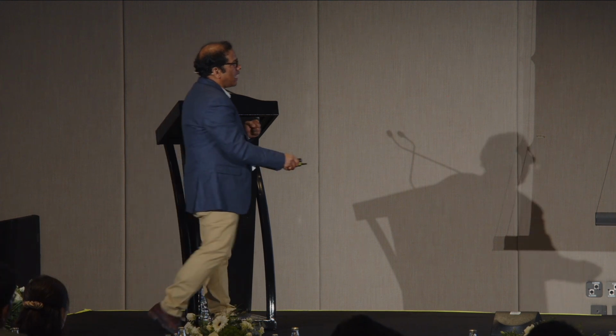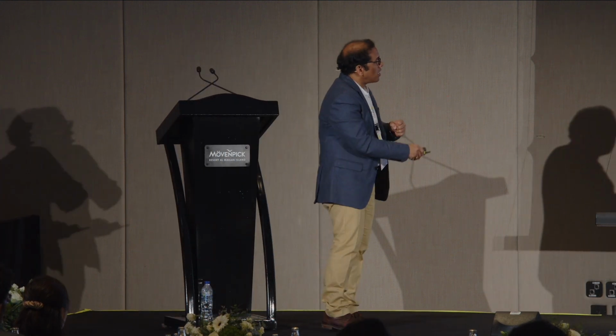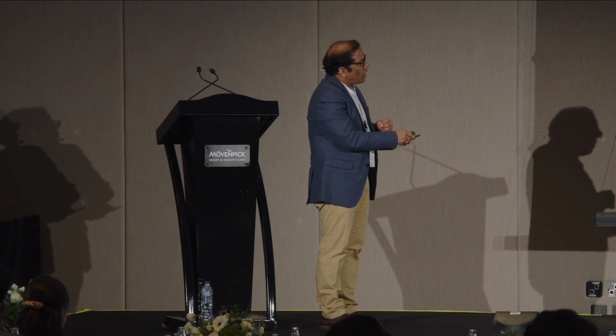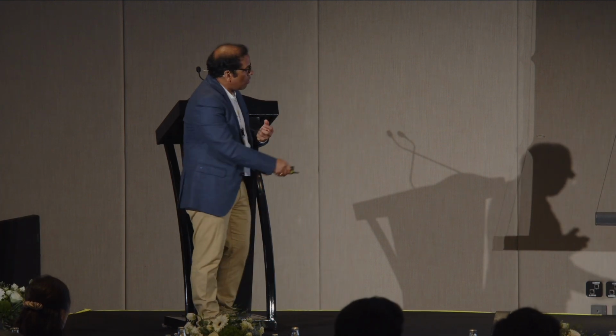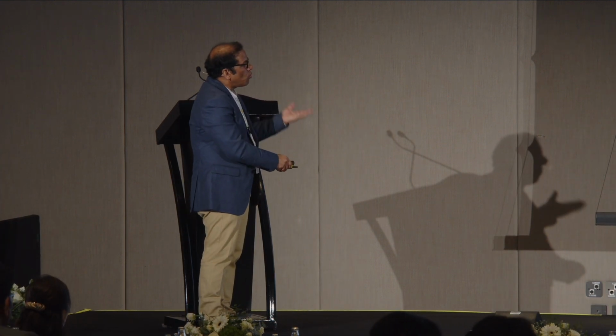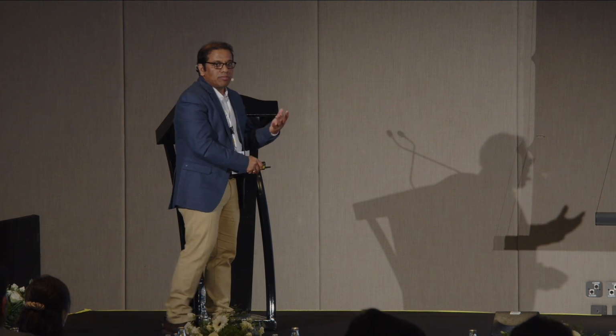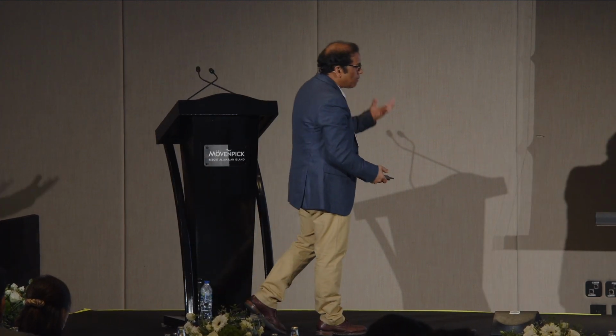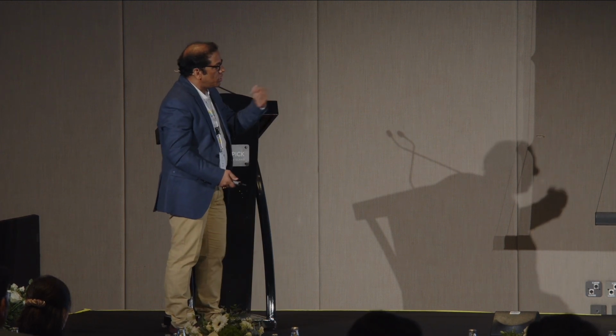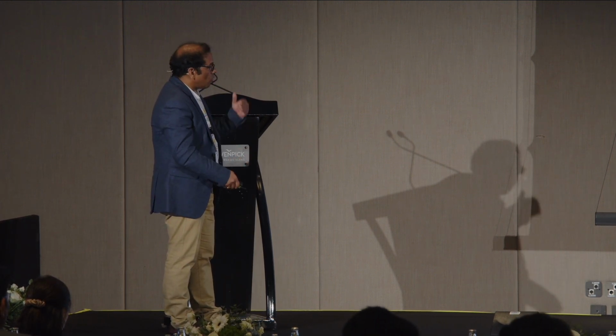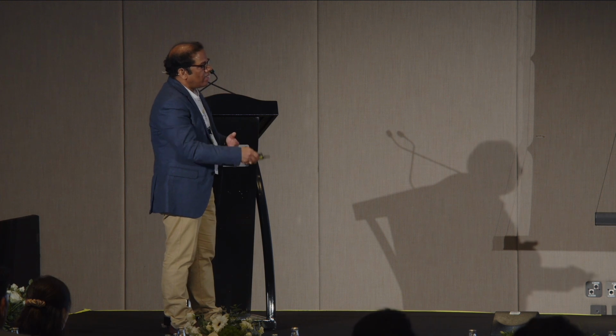So what we tried to understand from this work is that you have to connect a metal ion with redox active nature, otherwise electron migration issues occur, or you have to add a co-catalyst. Earlier, because of the D10 electronic configuration, it could bind the metal ion support but could not accept the electron, so catalytic efficiency decreased. But when we added platinum, it significantly enhanced the activity.